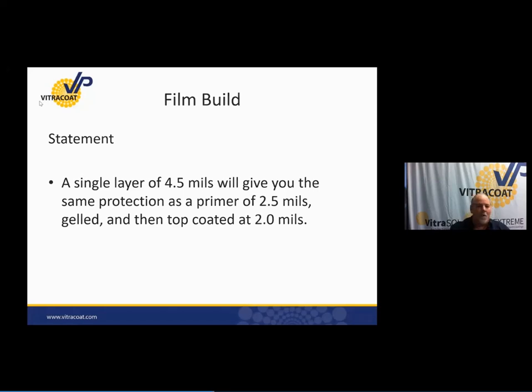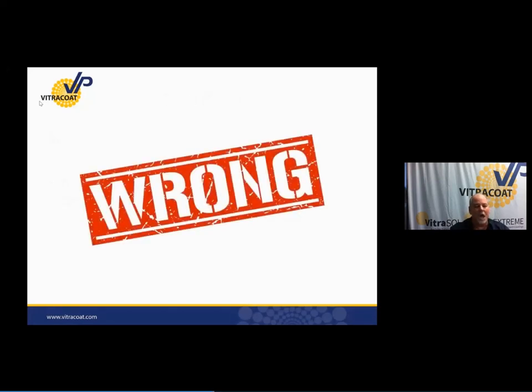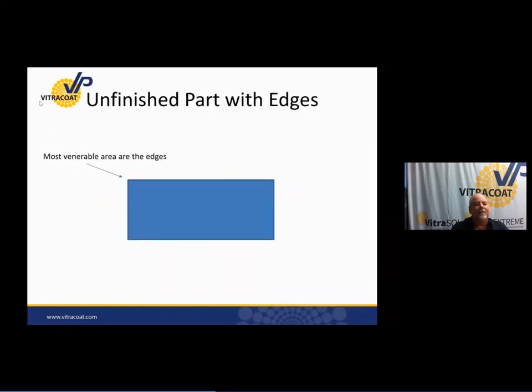The answer is no. That would be a big no. And the reason is simple. As I mentioned earlier, spraying on edges is difficult. It's hard. The material itself, whether it's a powder or a liquid, doesn't want to hang on an edge. It wants to flow from that edge. And if your part has edges and I try to hang 4.5 mils in a single layer, I'm going to have a very difficult time getting good coverage on those edges.